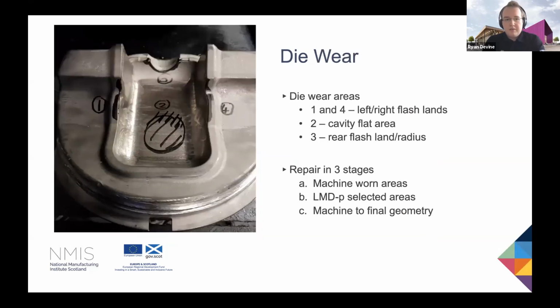So working with Mills Forging on this, we identified the four main areas that were the most problematic for wear. These areas were wearing more than many other parts of the dies, and these were the parts deemed the most responsible for failed components. So we have here on the die areas 1 and 4 highlighted, which are the left and right flashlands. This is essentially a mirror image of each other on each side. We have area 2, which is the flat part at the bottom of the cavity. And we have area 3 at the back, which is the rear flashland or radius section.